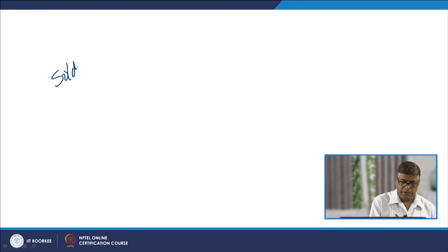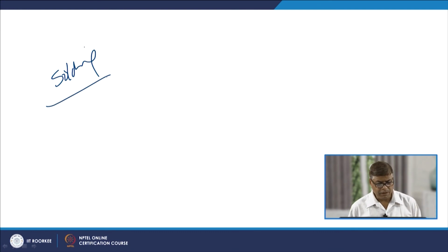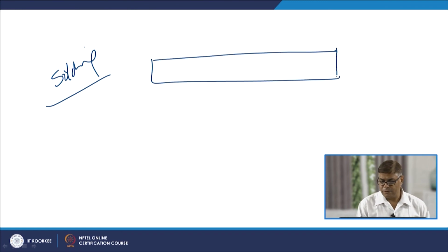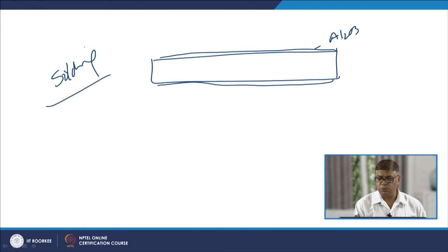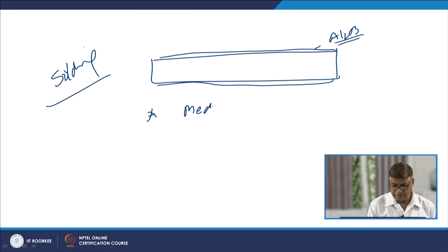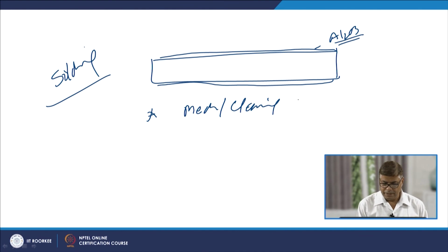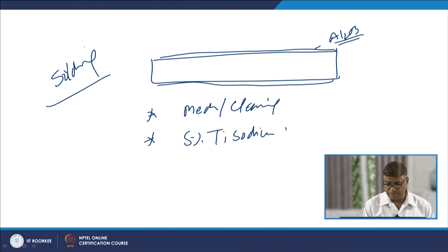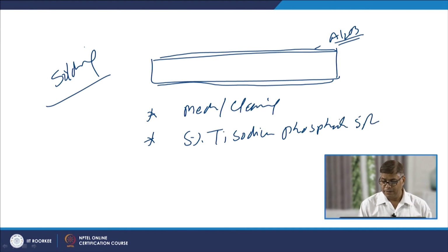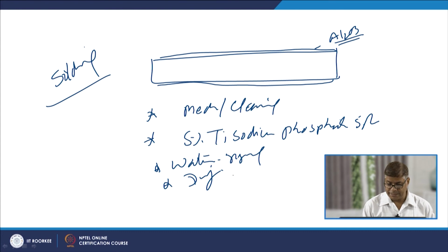Now, coming to the joining of aluminized steels by soldering. Here the presence of alumina matters, because wherever the aluminum coating is there, it will form oxide in the form of alumina. So, we need to do away with this alumina and aluminum coating, and to take care of them, basically mechanical and chemical cleaning is done, thereafter dipping of the aluminized steel in 5% trisodium phosphate solution, thereafter rinsing in water and drying of the sheet, and after this the sheets are joined by soldering.